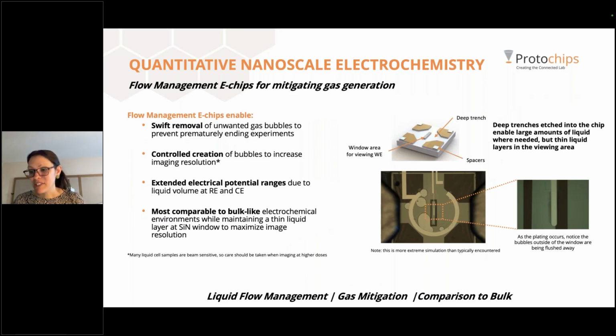From the gas mitigation side, again, you may be creating bubbles either because the chemistry generates them, or you may do it by accident as you are trying to optimize your conditions. The design of that smaller MEMS device, we call these our flow management chips, helps to create a flow channel through the chip that just sweeps away the gas bubbles as they're generated. You can see that the window area here is at a higher elevation, let's say, than the trench where the bubbles and such will be flowing through.